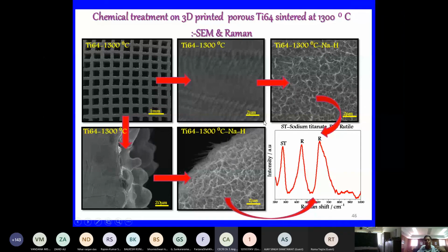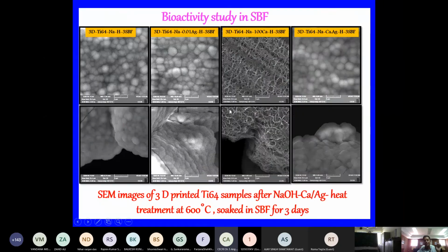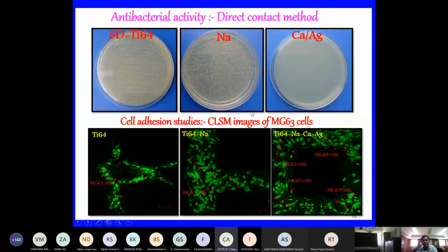So we try to develop different types of surface modification. You can see here also, because of this surface modification, this nanostructure layer of titanium oxide, where you can decorate silver, calcium, strontium, any other element on the surface, and we try to understand the property and how it is behaving. And you can see also we evaluate the bioactivity of this porous scaffold, and in some of the conditions we are finding that it is not forming the bone, and we try to understand the mechanism behind this bone formation happening in some conditions, and why some conditions are not forming any bone.